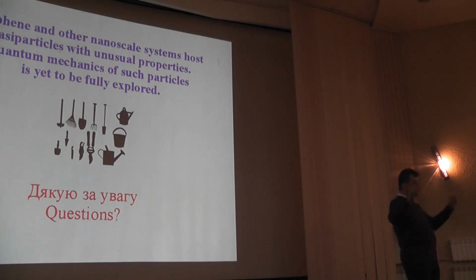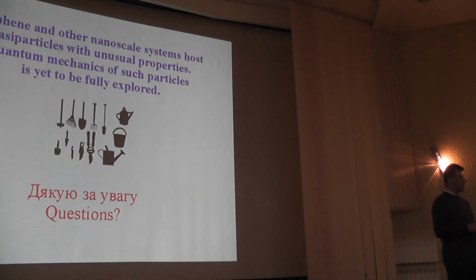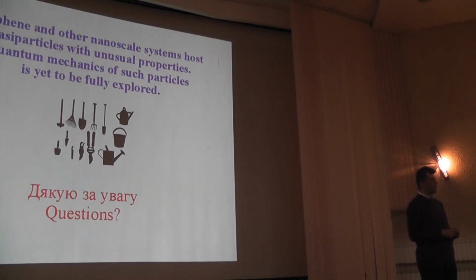If the wave function of the state is much wider than the size of the cluster, it doesn't really matter. And that's the case in the experiment. The cluster is about 1 nanometer in diameter, while the wave function extends to distances of 7 or 8 nanometers. Those collapsing states are pretty large. That's what happens in this particular experiment.